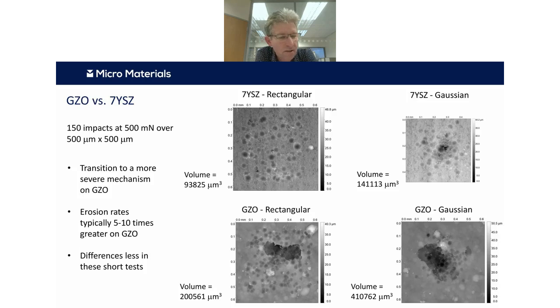So if we contrast the two different coating systems now, the GZO and the 7YSZ, what we can see here essentially is that there's a much bigger change between these two coating systems. So it's typically around, in the Gaussian ones, about 3 to 1, something like that, in terms of impact volume. And this correlates reasonably well with erosion rates, which are maybe a little bit higher than that, maybe 5 to 10 times higher. But in these short-term tests, it's quite encouraging that there's a reasonably good correlation between these two coating test data. And indeed, if we run these tests on, we would get closer correlation still.